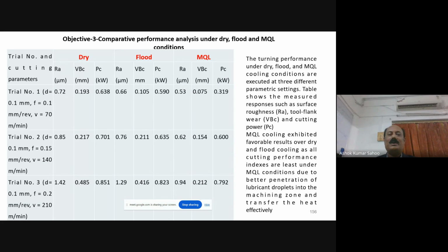Similarly, at 140 meters per minute cutting speed, and also at the higher cutting speed of 210 meters per minute with multi-layer coated carbide insert, the flank wear is 0.212 mm, which is well below 0.3 mm for finishing operation, and the Ra value is 0.94 micron, which is well within 1.6 micron under MQL environment. We can observe this under dry environment and flood environment, particularly